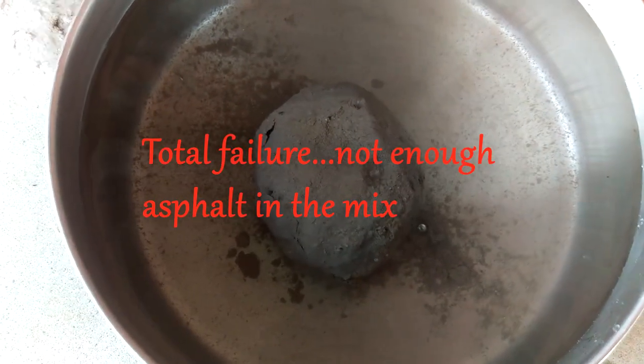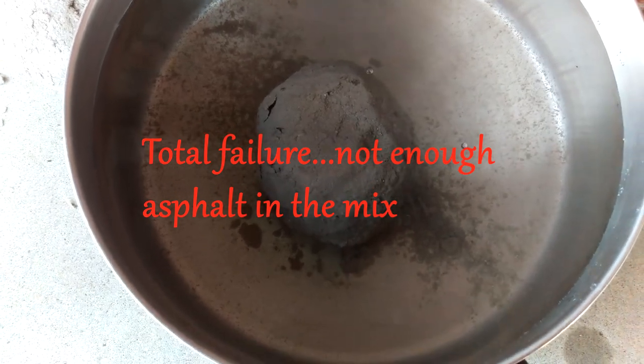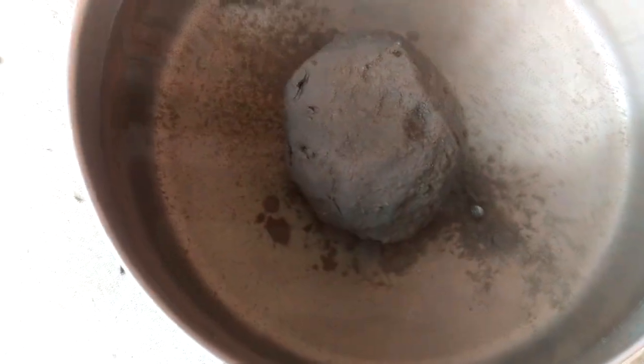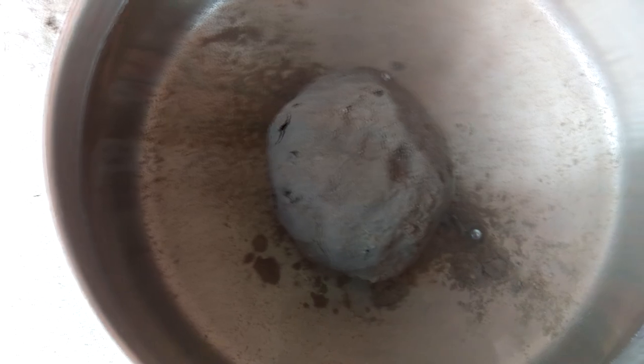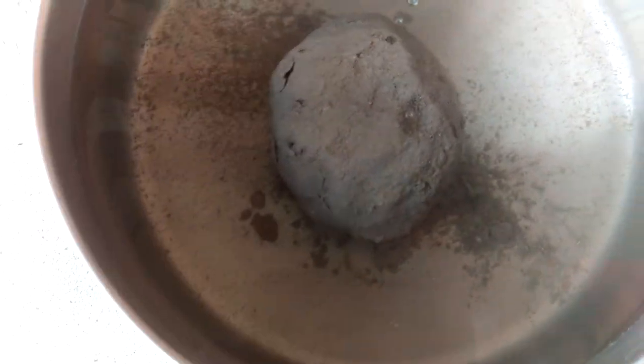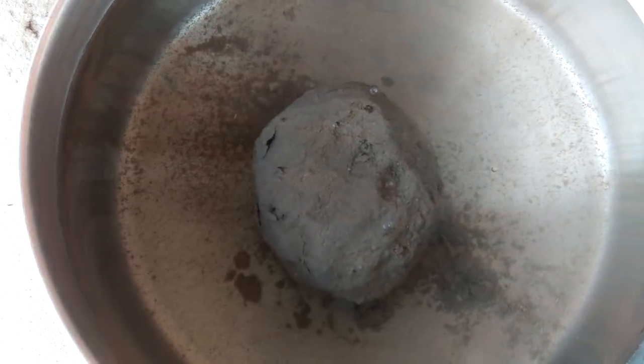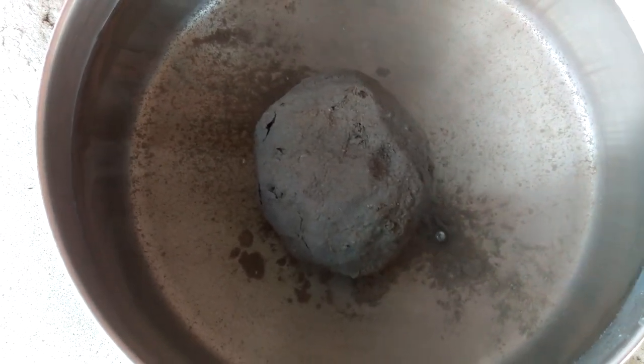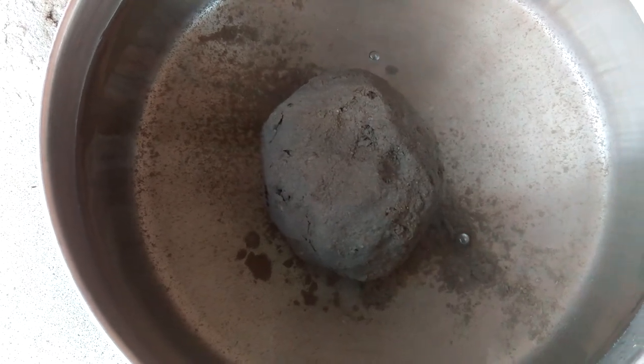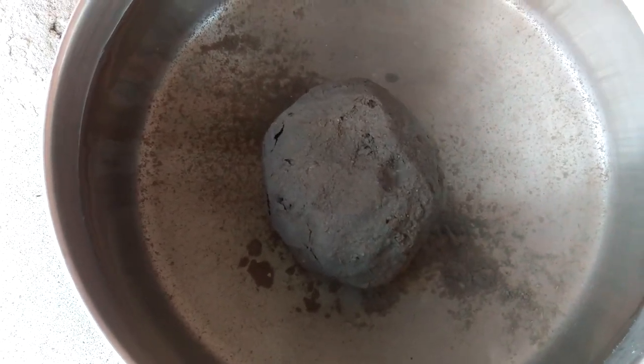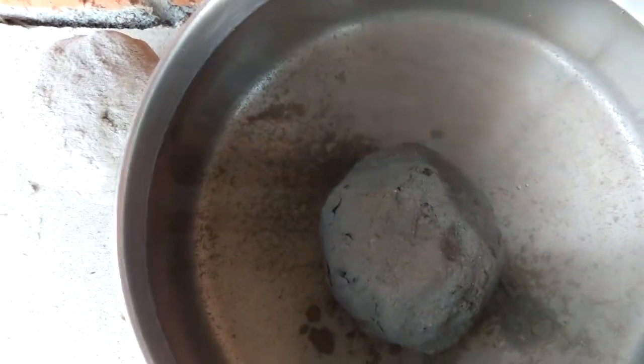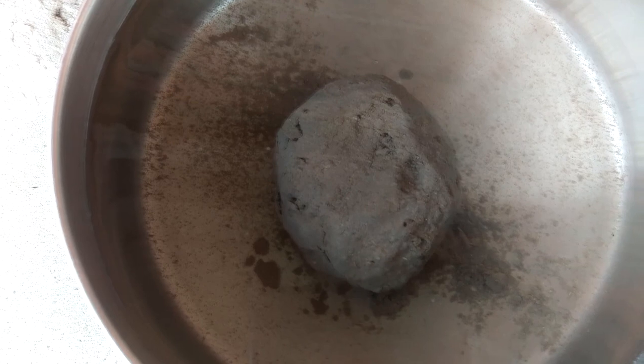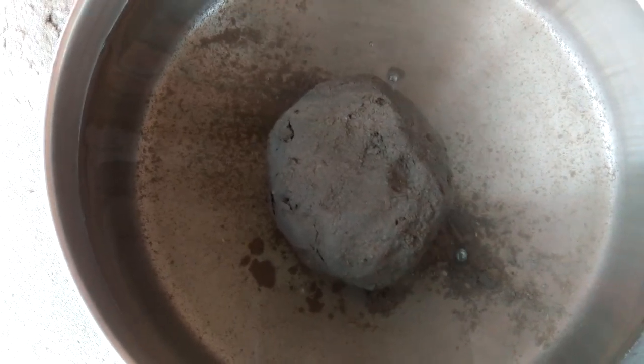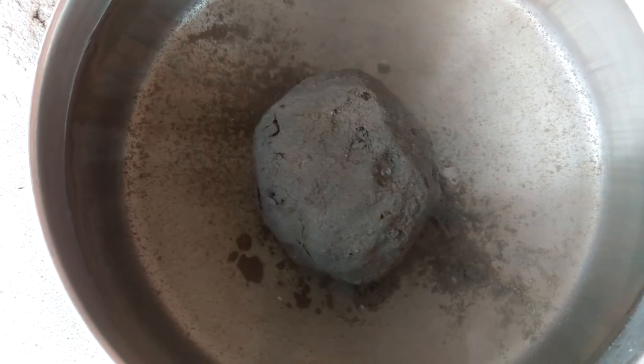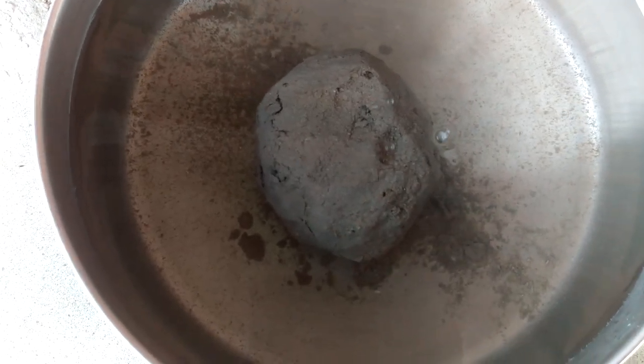It's been less than a minute, and you'll see that this ball is literally flaking apart from the water. And you see pieces of it coming off and settling in the bottom of the pan. That's not the greatest sign. Tells us that we do not have nearly enough stabilization in this. And the fact that this stuff is flaking the way it is tells me also that our clay content is a little low. I'm just not happy, but it seems clear that we're going to have to do some more testing and actually add a whole bunch more emulsified asphalt to this mix to stabilize these bricks as best we can.